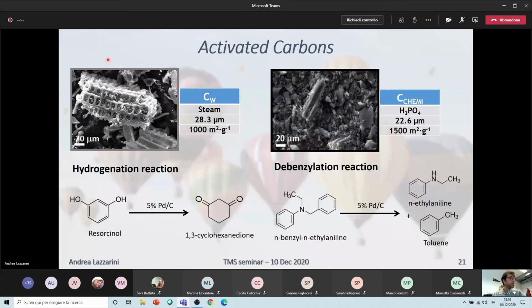And the explanation that we gave is that this catalyst, having fewer functional groups on the surface and a more extended and regular graphene-like character, was able to physisorb the benzene rings with pi interaction, let them travel towards the active phase, then on the surface of the nanoparticles make the magic of the catalysis happen, and then, once you no longer have the pi interaction, release the products. While in this case we have a less regular carbon with more oxygenated groups. Therefore, it was less prone to let these aromatic rings adsorb on the surface and perform the hydrogenation reaction on the rings, favoring the debenzylation reaction instead.